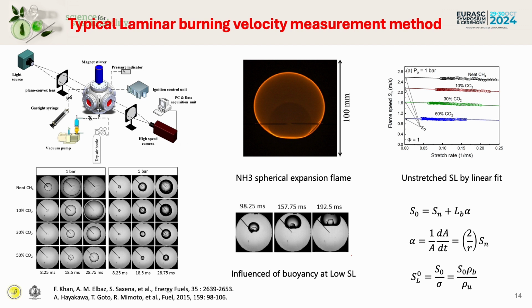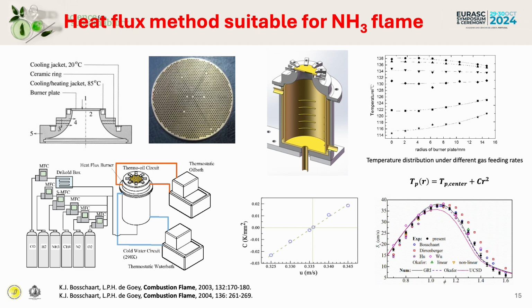But we are on the Earth, so flames are always influenced by buoyancy. Ammonia is a very low reactivity fuel. Its flame speed is just one-fifth of typical natural gas, so you can see it is greatly influenced by buoyancy. This causes lots of systematic errors. The heat flux method is another typical method suitable for measuring laminar burning velocity, especially for low-speed flames like ammonia. This method was invented by Professor Philippe de Goey in the early 2000s.